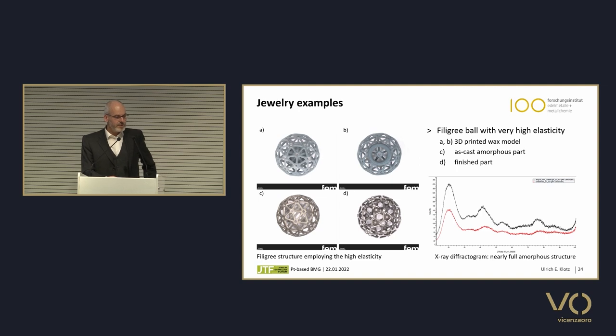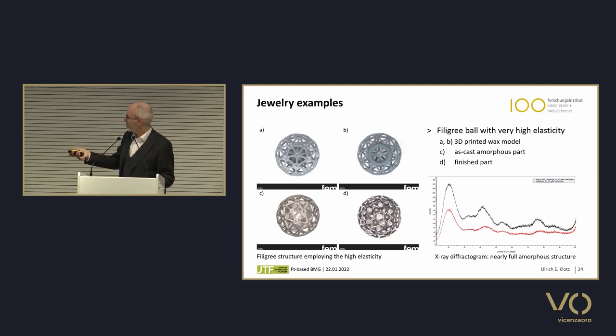Then we tried another example. This was a small sphere. It has maybe 10, 15 millimeters in diameter. You see the 3D printed parts. It has a mesh structure on the surface. And we could cast it without problems. It was filling very well. This is the cast part. You see, again, the surface is already looking very good. And this is after finishing.